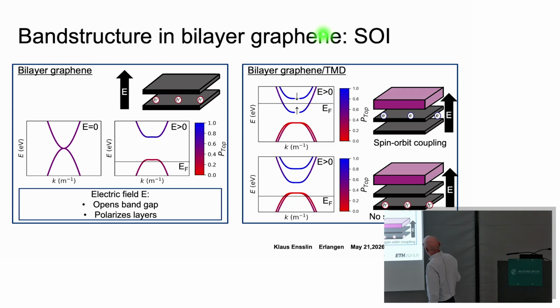So what you can do is you can place a piece of transition metal dichalcogenide. Actually, it doesn't matter what you take, whether it's tungsten diselenide or molybdenum disulfide. They all act about the same way. It behaves like an insulator, and this insulator injects spin-orbit interaction in a similar way as a superconductor injects superconductivity in a neighbor. We call it proximitized spin-orbit interaction. And it has a very short decay. So in other words, you see the band structure here. You see the upper band has split now because of the presence of this TMD next to the graphene.